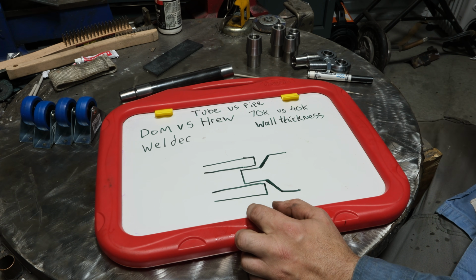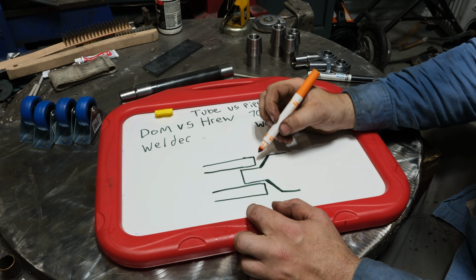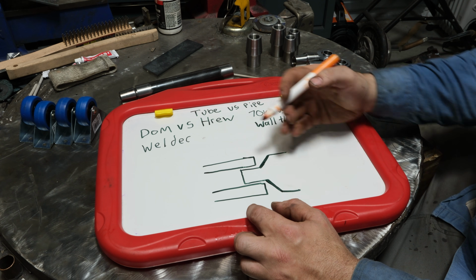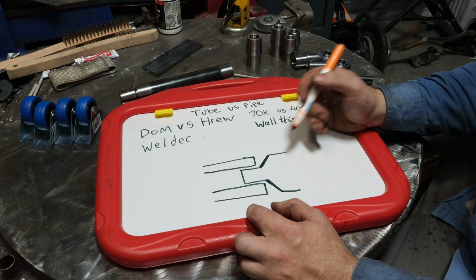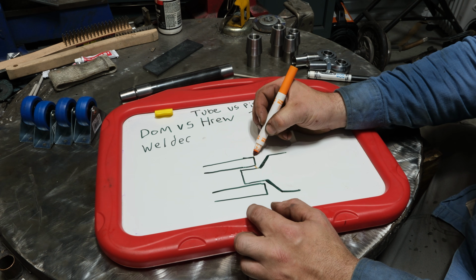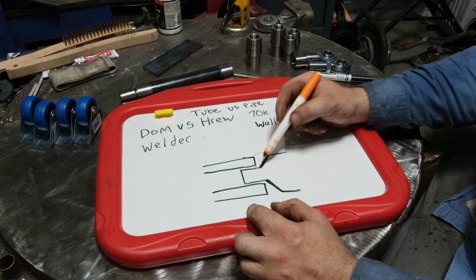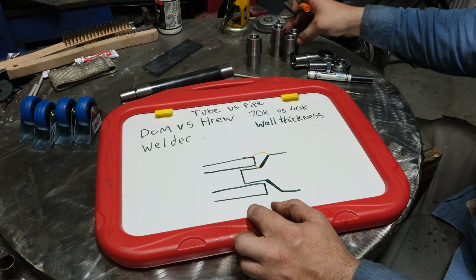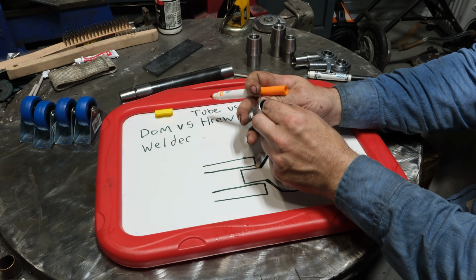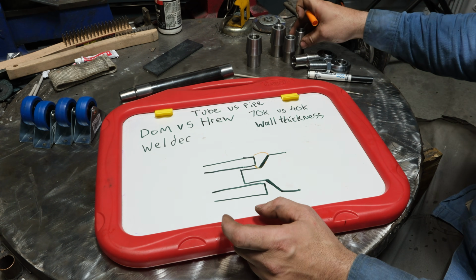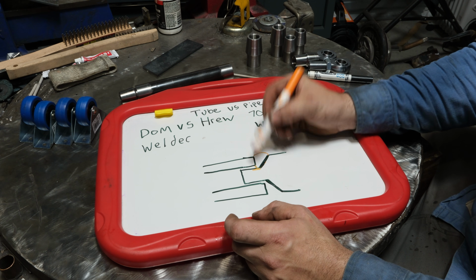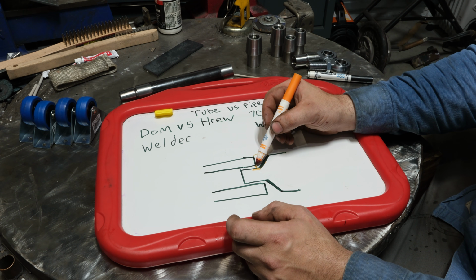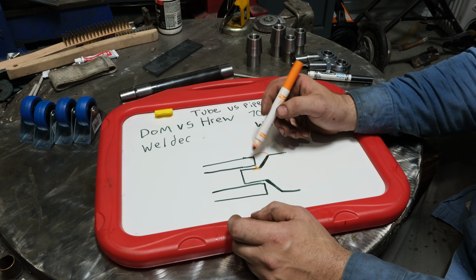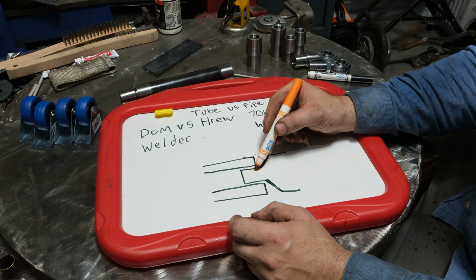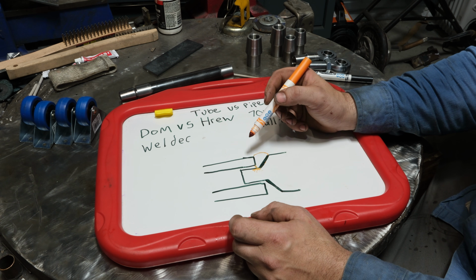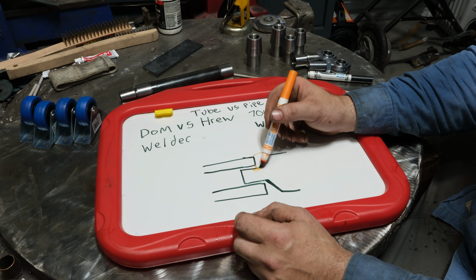Now, another thing that's important here is how much weld do you actually need on one of these? And what I mean by that is this. A lot of guys, when it comes to welding, you want full penetration, full weld, to where this whole thing would be weld, just like that all the way down. The problem is when you look at these thinner ones, that's like less than 1/8 of wall thickness in this section right here. If you try and do a hot full penetration TIG weld or stick weld or whatever in there, what's going to end up happening is you're just going to melt those threads in there to where now you're really screwed and the tap might not even fix them.